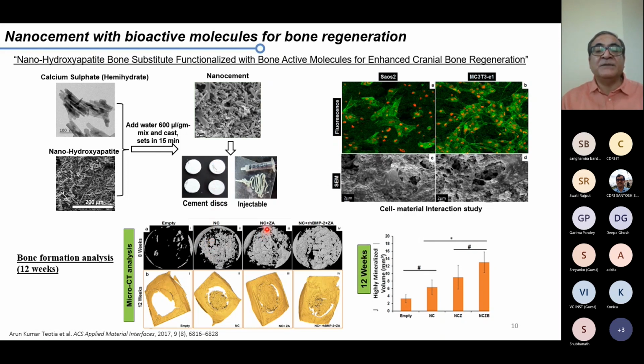But if you put it with cement and ZA, which is a bisphosphonate, an anti-catabolic agent, then you have more filling of the bone. But if you use BMP, which is anabolic, and ZA, you have almost complete recovery of the bone of this defect area. It has also been shown by the micro-CT analysis, which you can see here.